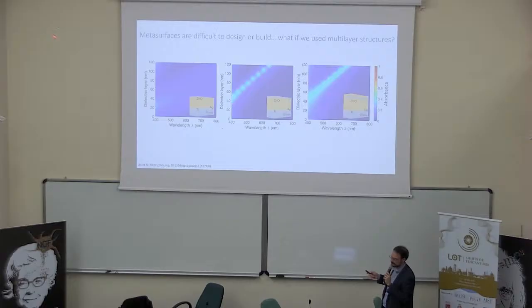see, especially because we need this titanium layer, the silver and the zinc oxide and the dielectric, you get an absorbance spectrum that is close to zero. So it doesn't absorb. If you start to make it like a Fabry-Perot, you start to get this absorbance according to varying the thickness of the dielectric constant or the dielectric cavity. You can get different wavelengths where it interacts.